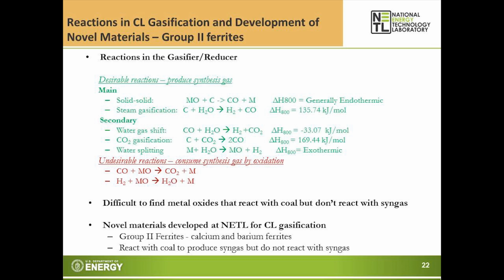Unfortunately, most of the metal oxide oxygen carriers participate in the reaction, and it's very difficult to control the reaction at the syngas stage. So we have developed here at NETL some novel materials for chemical looping gasification. These are group 2 ferrites, calcium and barium ferrites. And now they have unique properties. They can react with coal to produce syngas, but they do not react with syngas to produce CO2 and water. So we can control the reaction at the syngas stage.